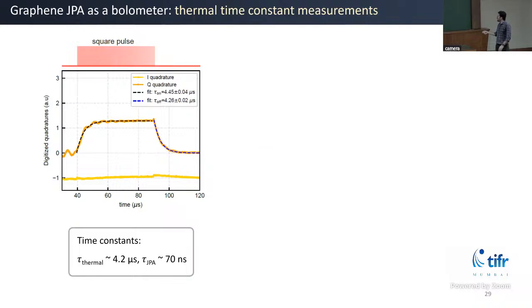So then we also checked why this is not very fast. For that, we also measured the intrinsic time scale of our resonator, and we found that this is quite fast, actually 70 nanoseconds, because it's a low Q, directly coupled device. So it should be very fast. And the device is limited by this thermal time constant of 4 microseconds.